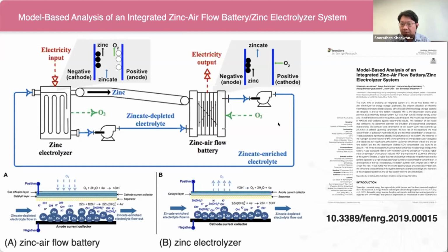Increasing zinc cation concentration was able to suppress the hydrogen evolution reaction and increase the current efficiency of the battery because of the lessening of the reversible potential difference between the zinc electrode reaction and the hydrogen evolution reaction. As regards the electrolyzer, the results show that its performance was dominated by zinc cation concentration and electrolyte flow rate. When zinc cation concentration increased together with the flow rate, current efficiency significantly increased. Further, the charge energy was reduced due to the enhancement of zinc cation diffusion to the electrode surface. Yet, increasing potassium hydroxide concentration does not directly improve electrolyzer performance, but contributed to the increment of the saturation limit of zinc cation, which enhanced the electrolyzer performance.